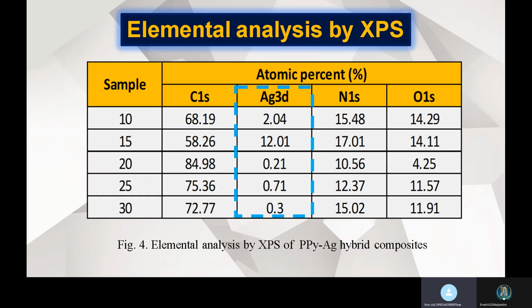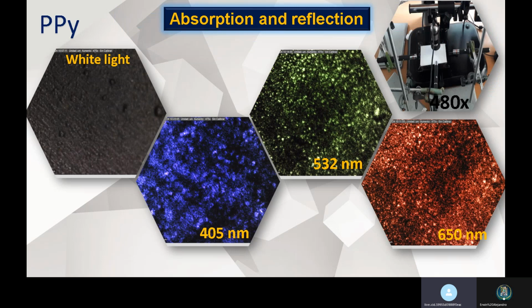Carbon, nitrogen, oxygen, and silver were detected. The atomic percent of silver varied from 0.21 to 12.01. Finally, absorption and reflection has been studied by optical microscopy. The photos were taken with a magnification of 480x.